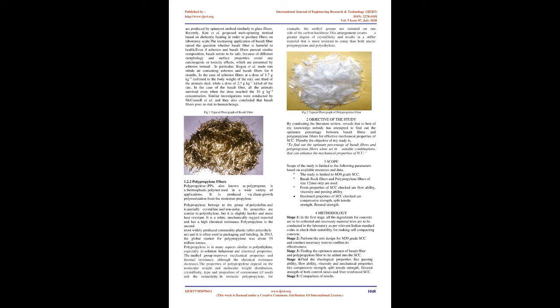Differences in terms of composition and elements concentration give differences in thermal and chemical stability and more or less good mechanical and physical properties. Overall, the manufacturing process of this kind of fiber is similar to that of glass fiber, but with less energy consumed and no additives, which makes it cheaper than glass or carbon fibers. Using a natural volcanic basalt rock as raw material, basalt fiber is produced by putting raw material into a furnace where it is melted at 1450 to 1500 degrees Celsius.